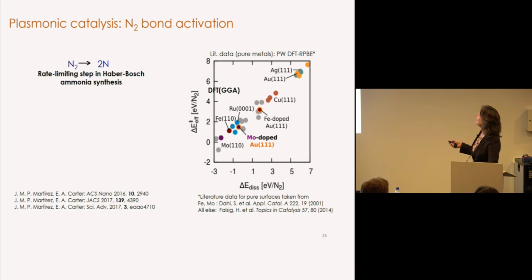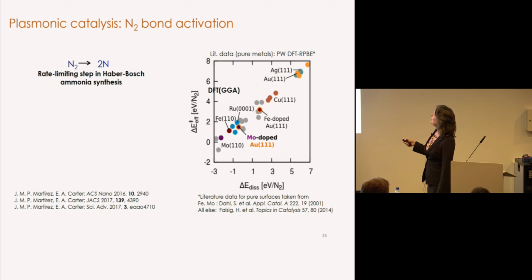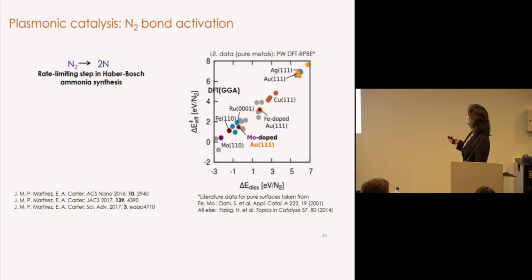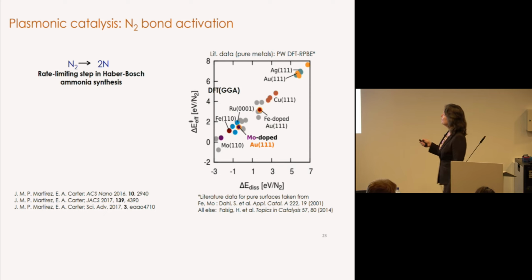Okay, so let me say that, as I mentioned, we wanted to look at not just dissociation of H2, we wanted to look at dissociation of nitrogen. Of course, that's much harder. It's a triple bond, and that is the rate-limiting step in Haber-Bosch ammonia synthesis. And this is data that we've superimposed some of our own results on at the DFT level, comparing the effective activation barrier to the energy, the exothermicity or endothermicity, so the thermodynamics, of dissociating nitrogen.